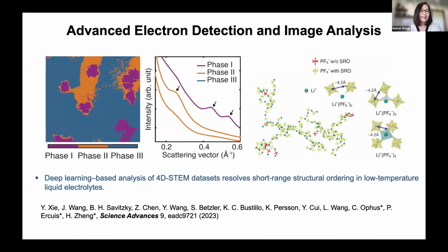Here, very briefly, this is an example of our work in collaboration with Colin Ophus when he was still in NCEM, and Peter Ercius at the NCEM of the Molecular Foundry. We use 4D STEM to study the low temperature electrolyte, and using machine learning and deep learning based analysis of 4D STEM datasets, we resolve the short-range ordering in this low temperature electrolyte. We found mechanisms similar to this high concentration electrolyte, and found this multiple, like 2 lithium ions.